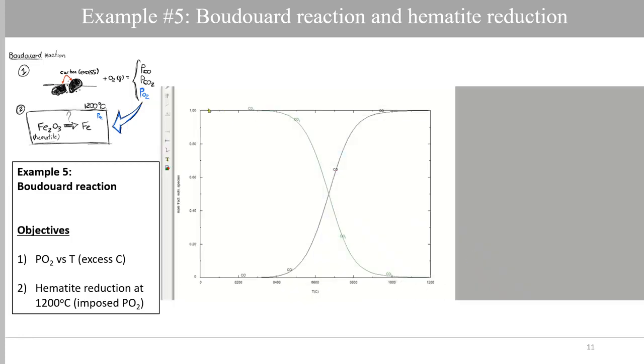So now you see that you have an evolution of a gas phase that contains mostly CO2 up to a gas phase that contains mostly CO at higher temperature with a shift around 700 degrees Celsius, which is predicted by the Boudouard reaction. That's great.